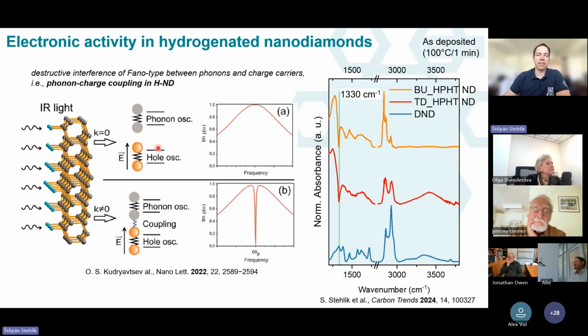the conductivity. And I was quite happy that this paper from Ivan Vlasov's group appeared some time ago, and it explains this feature, because we observed that, but we were not able to explain it. But this paper appeared and explained that it's coming from the Fano interference between the phonons. That's why it's the phonon frequency, the discrete state of phonons, and the continuum of the charge carriers. So actually, this feature appearing signalizes that we have some charge carriers inside and/or on the surface or close to the surface, and it's quite nicely correlating with the conductivity.